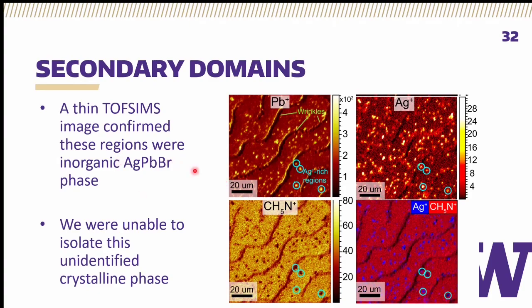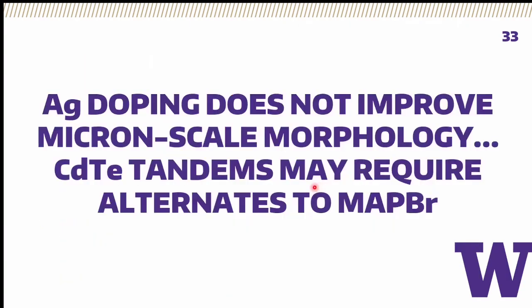indicating that this is some previously unidentified phase in the silver-lead-bromine phase diagram that potentially someone else could, either through metastable methods, through strain or something, synthesize in the future and identify as a potential loss. This could also be interesting for degradation experiments on PV devices, as these silver-lead-bromide phases could be contributing to performance loss in those as well. So unfortunately, it does not improve micron scale morphology the way doing the silver doping improves nanoscale morphology. And so methyl ammonium lead bromide might be a non-starter when trying to make cadmium telluride tandem devices.